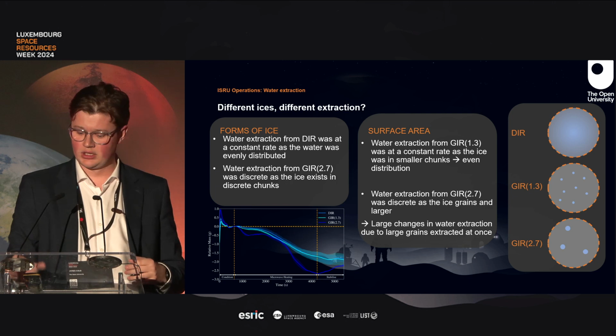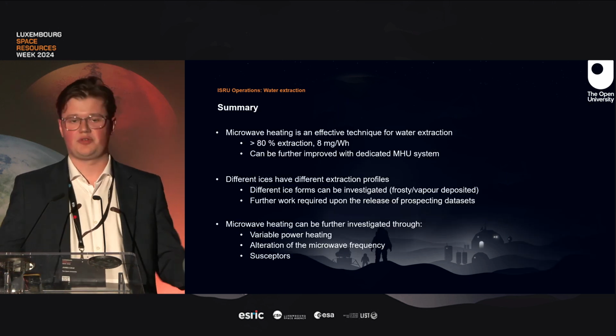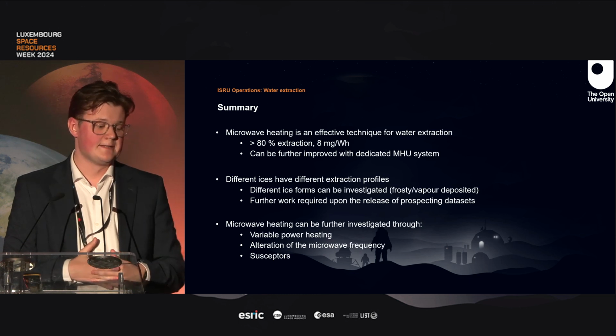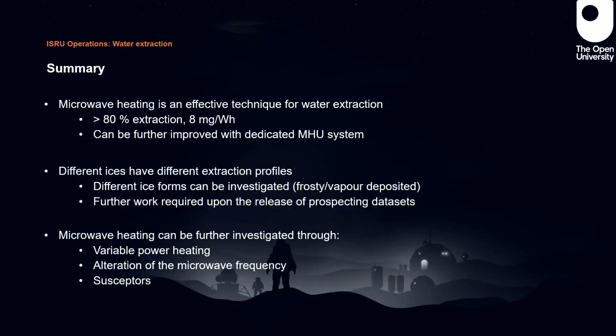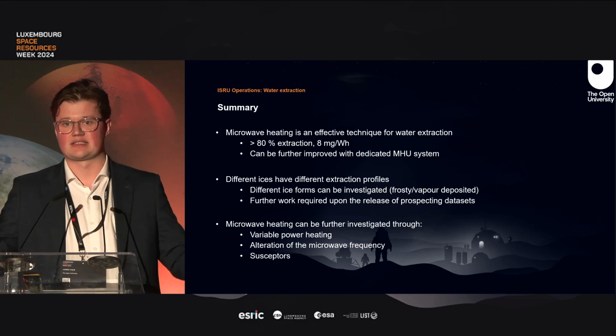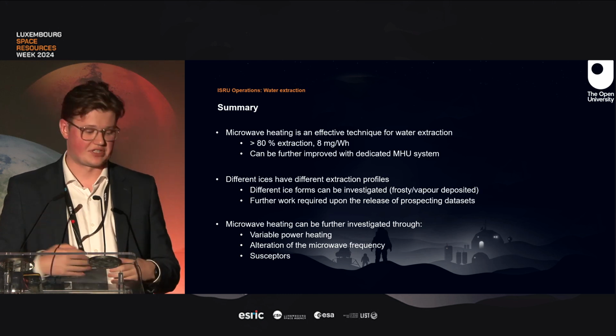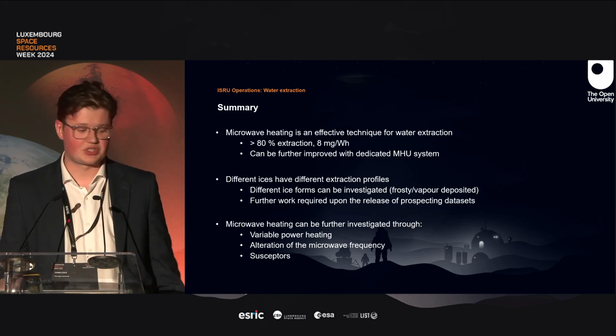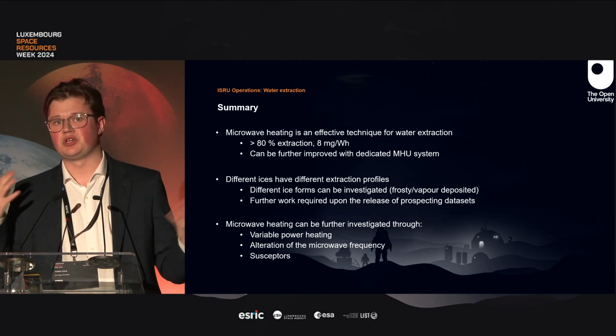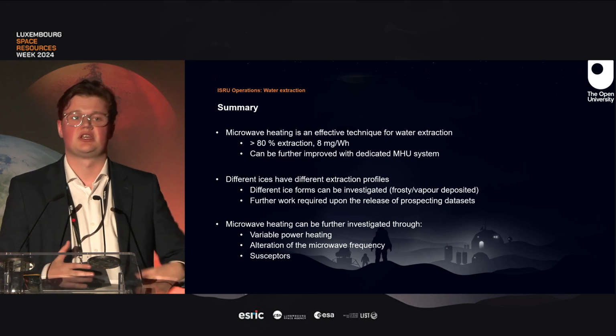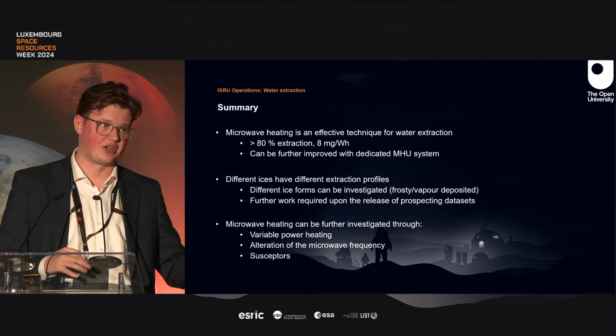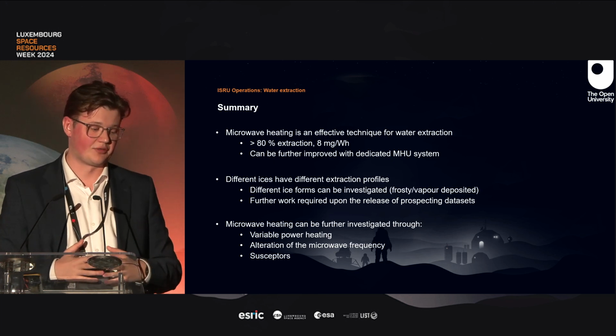So in summary, microwave heating is actually quite an efficient technique for extracting water. And it can be further improved with a dedicated system. This system is meant for sintering. So if we could build a system that's meant for water extraction, not only could we get better efficiency, we could build in sort of a cold trap system like the Luvex system. And then we could also see how the scale improves with bigger samples, because we've always been limited to what the size of the cavity is. We've seen that different ices have different extraction profiles, and we could explore this further with further sample types, whether that be different grain sizes or using frosty ices or whatever forms of ice we can think may be possible.